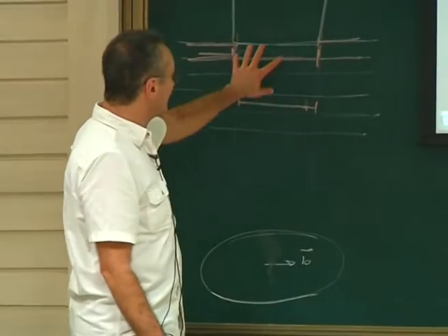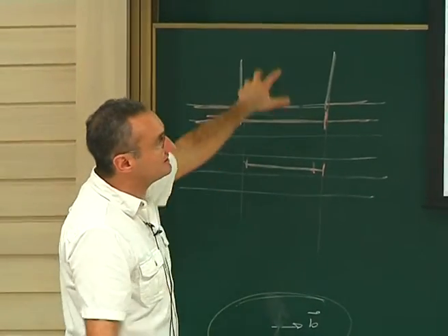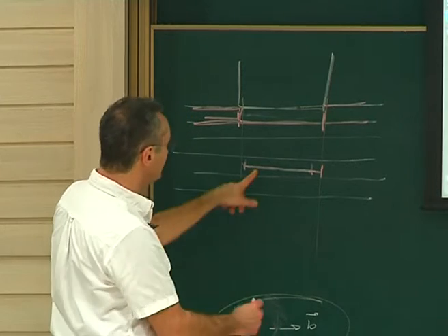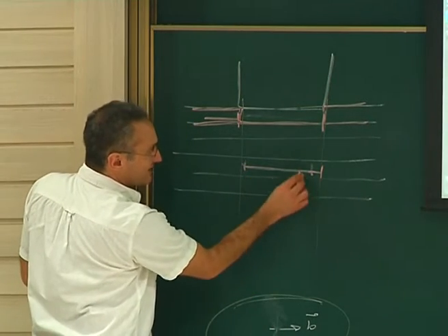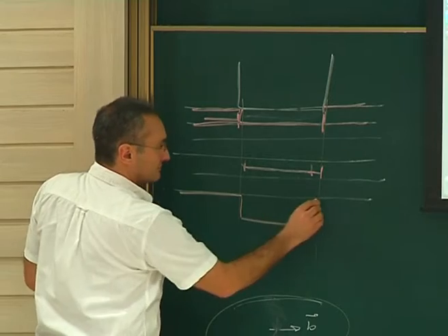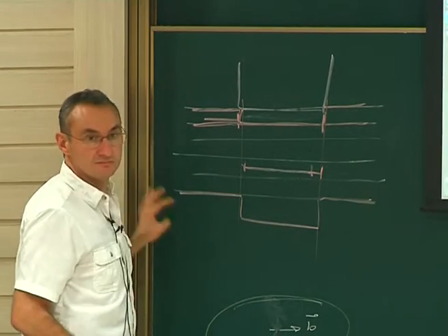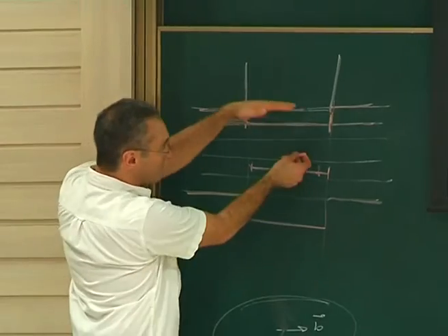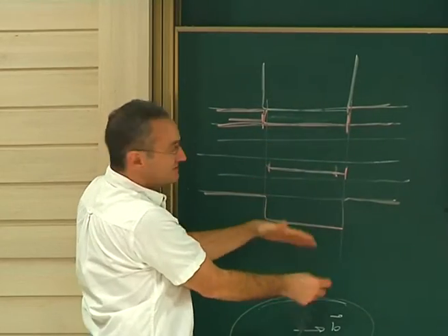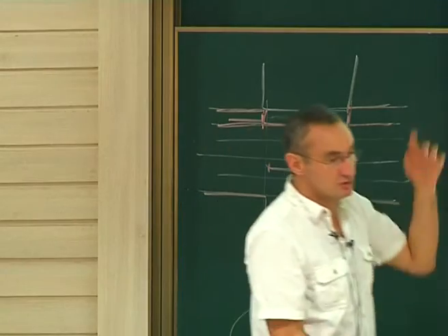Okay, for the prismatic loops. So prismatic loops are these things. So you have vacancy and interstitial always at the same place, accommodating some punch or extrusion. So if these guys, let's go further, if these guys reach the bottom surface, then you will have a burst here, which corresponds to the extrusion. Okay? These guys leaving here. And in fatigue, this happens. You have some prismatic loops which reach the surface, and this creates some extrusion. Okay? So this is what you see here.